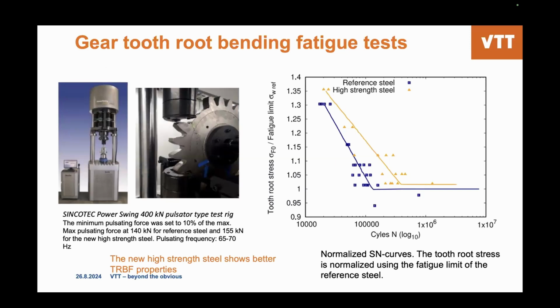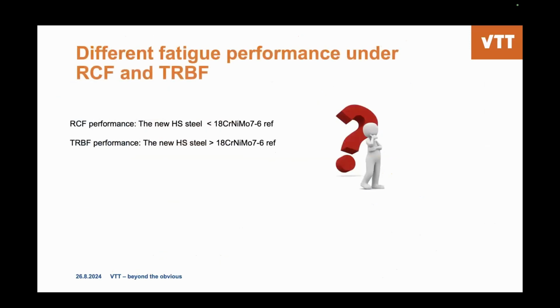So, a small summary: we have characterized these two materials through rolling contact fatigue test and tooth root bending fatigue test. It shows the new high-strength steel is less good compared to the reference steel in rolling contact fatigue test, but it outperforms the reference material during the tooth root bending fatigue test. So it raises the question, what will be the cause?